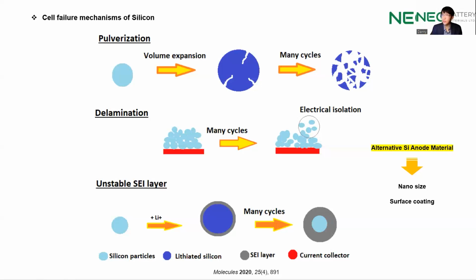Now, you see in the graph here, unstable SEI layer. So this is a layer that builds onto the silicon surface, and if it thickens too much, the silicon becomes unusable. Second, the poor electrical conductivity results in poor cycling performance and rate capability. So this is the charging capability. So to overcome these problems, substantial research has been conducted for effectively accommodating the large volume changes and enhancing the electrical conductivity of silicon during cycling, so during the charging cycles.